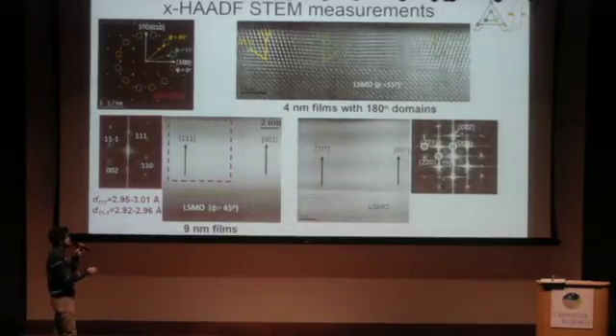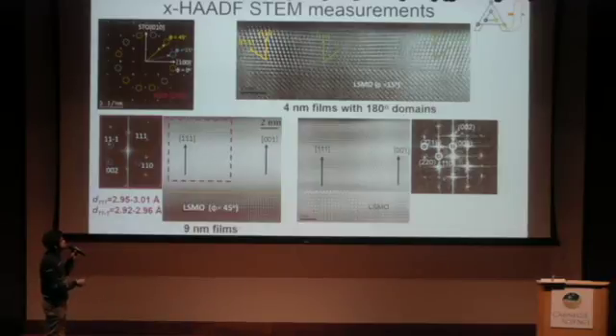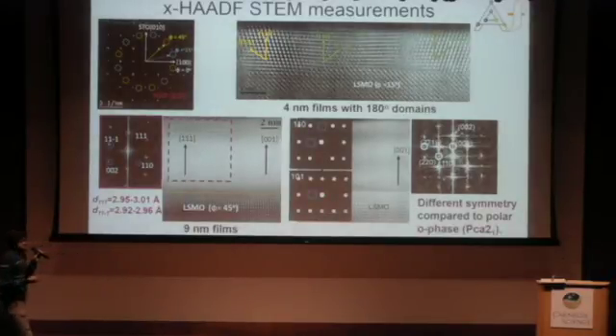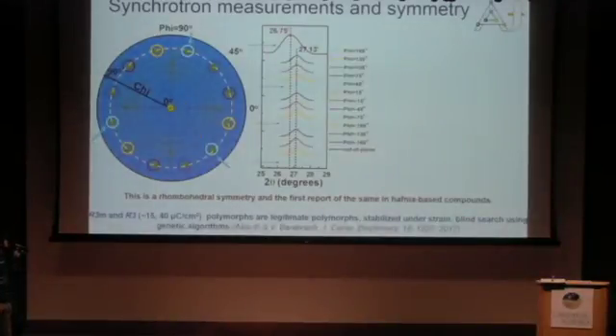Same thing if you analyze the 001 domain, you do find some spots which are forbidden in a Pca2_1 orthorhombic phase. What phase is this? To do that, you go to the synchrotron, go back to this pole figure, analyze, let's say, all these spots, theta 2 theta scans around these spots. And here let's concentrate on one particular domain. Here we clearly see that there is a 3-to-1 multiplicity for the 111 peaks. And this is a clear indication that what we have is a rhombohedral phase, which has been reported, but not in the context of ferroelectricity, and which is what excited our theorist, Jorge.